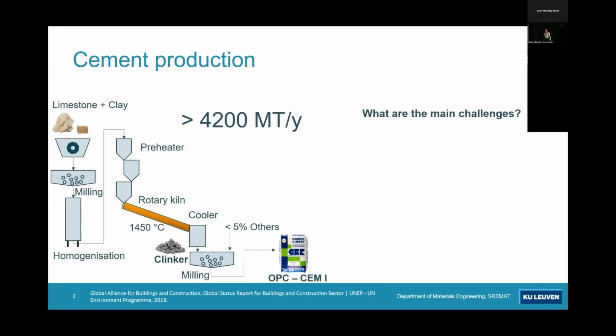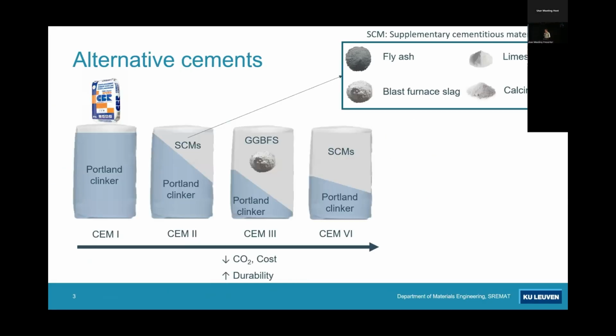What is in cement is mainly Portland cement, which is Portland clinker. And Portland clinker is an energy-intensive phase. It's composed of different mineral phases which can react with water. But to make this phase, you have to calcine large amounts of limestone, which results in a lot of CO2 emissions. So what has been done in the past is to reduce the amount of Portland clinker with various waste residues, fly ashes, blast furnace slags, calcined clays now being very popular, and limestone, while maintaining most of the properties, which for concrete producers and cement producers means compressive strength.